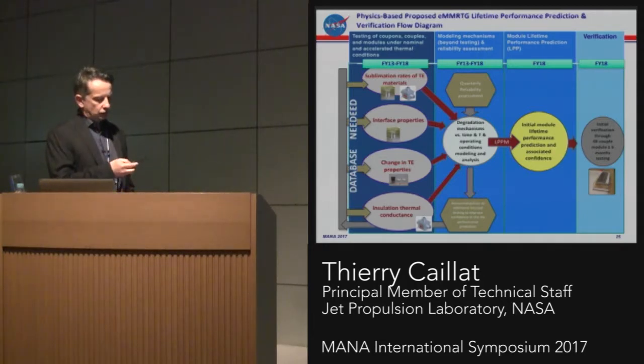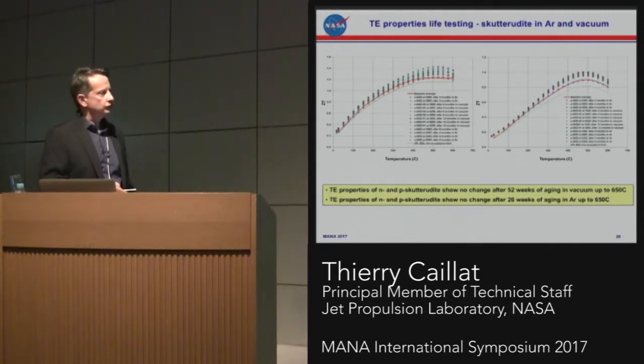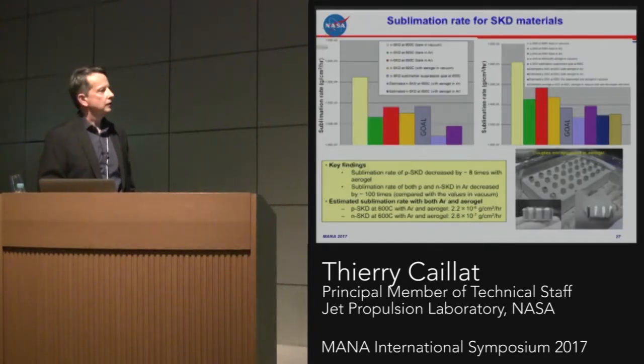We're also looking at this from a reliability and statistical point of view, and we have a whole model to do that. So far, we've been testing the skutterudite properties for over 2 years. And what we see is that, if anything at all, the ZT is increasing after 2 years of testing compared to the baseline materials, both for the N and P type. So that's not an issue. The materials are very stable up to 650 C.